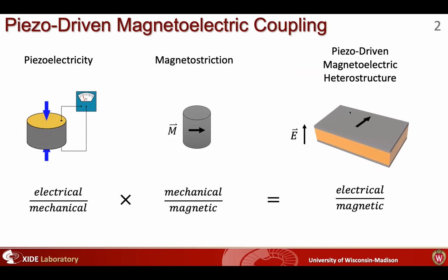So with piezo-driven magnetoelectric coupling, I'm trying to use an electric field to generate a lot of strain in my piezoelectric material, and through strain coupling, manipulate the magnetism of a ferromagnetic metal on top. The effect that we wanted to achieve was this 90-degree rotation of in-plane magnetism, in the hopes of using it in a magnetoresistive tunnel junction for memory devices.